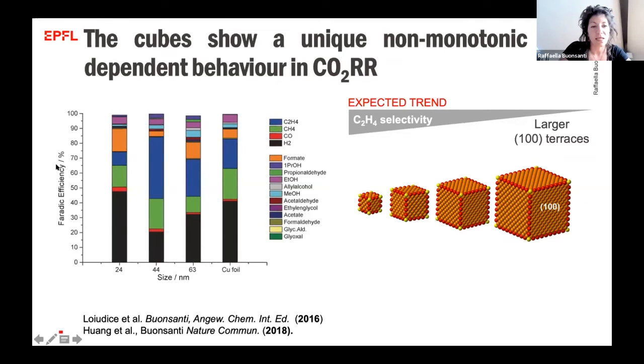Here, what I'm reporting is the Faradaic efficiency, which indicates how many electrons are converted into certain products. And here, the black line is the hydrogen that is produced, because the hydrogen evolution reaction will always be competing with the CO2 reduction reaction, as it is kinetically more favorable. And here you can see that the 44 nanometer cubes are producing less hydrogen and much more ethylene compared to the other sizes.